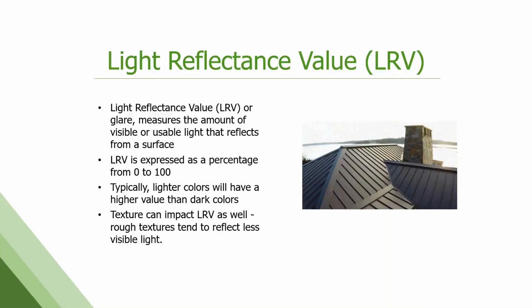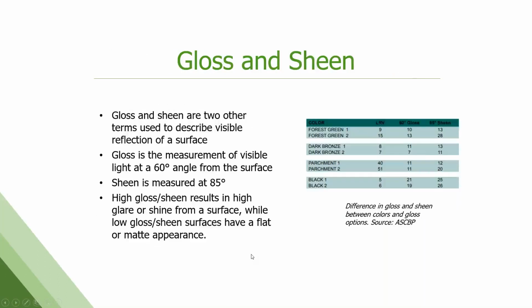But there are ways to adjust this, because glare and shininess can be objectionable on a final installation. So you can play with texture, and there are ways to get a more matte finish by putting additives in the paint. And that is controlled by what we call gloss and sheen. These are two properties that we can actually measure on any painted surface. Gloss is the measurement of visible light at a 60-degree angle. Sheen is measured at an 85-degree angle. So with a high gloss, high sheen value, you're going to have a very high glare or shiny surface. But low gloss, low sheen will be very flat or matte in appearance and not as shiny. We have some examples there of what that looks like.